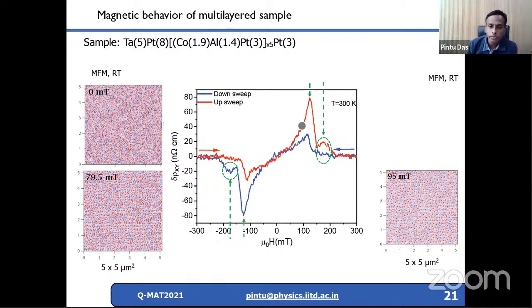To move skyrmions, you need to give some kind of spin transfer torque to this spin system. Consider, for example, domain walls. In domain walls, typically the critical current density is much higher than for skyrmions. Skyrmions you can move with much smaller current. But we have observed, and it is also in the literature, that with a small current you can move them, but in real materials you have pinning centers. So they move around the pinning centers if the current is very small, and sometimes at the pinning center the interaction can annihilate them.